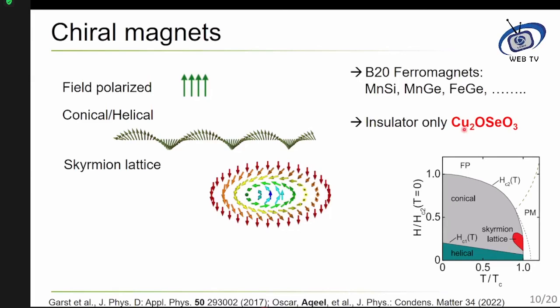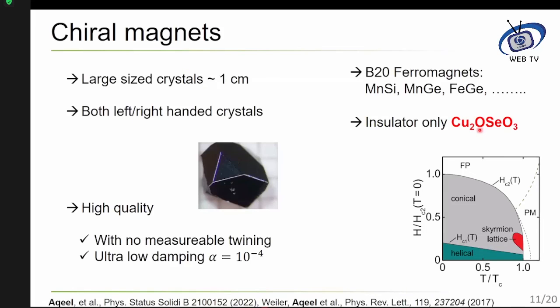Here, the magnetic atom is only copper and is distributed in some specific places. This is a magnetic insulator and has very low magnetic damping. We grow these crystals, and these crystals are very high quality. In terms of damping, it has 10⁻⁴ damping. Damping simply means that if you send some information inside a spin wave, it can travel a very long distance before it is diminished.